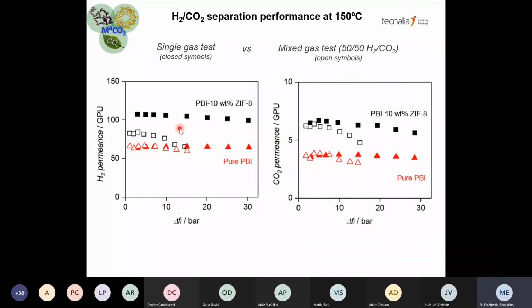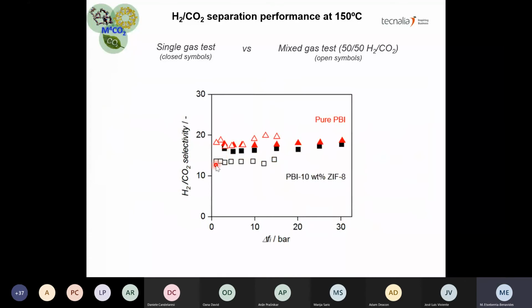At high loadings, CO2 is adsorbed in the aperture of the ZIF-8, and therefore as CO2 concentration increases, the ZIF-8 nanocage gets saturated, and therefore the fast diffusion pathways of hydrogen and CO2 through the ZIF-8 may be hindered. The hydrogen permeance is more affected by this competitive sorption, and therefore, for the mixed gas selectivity, a lower value was obtained for the mixed matrix membrane.